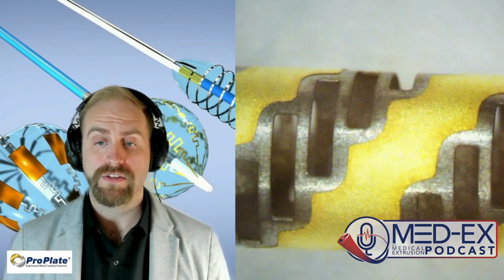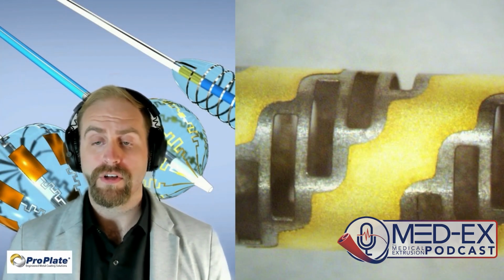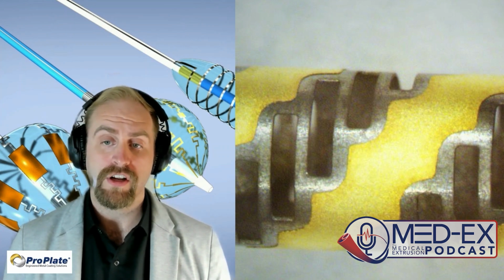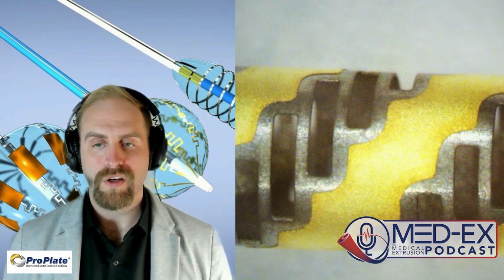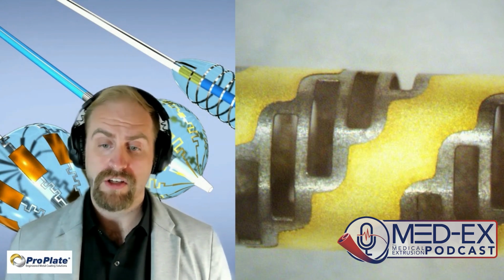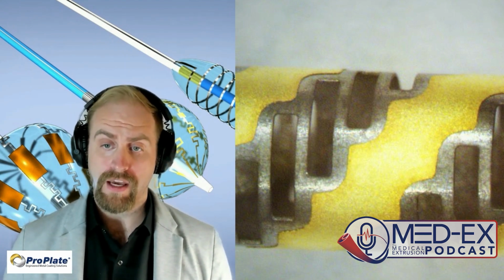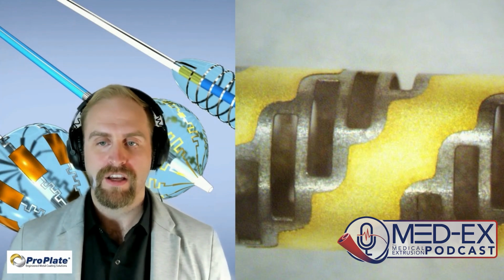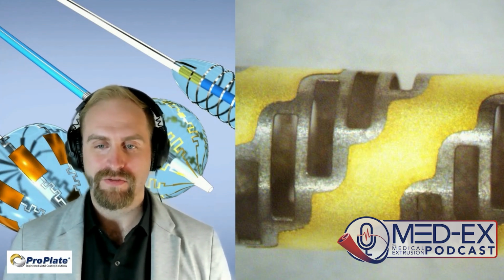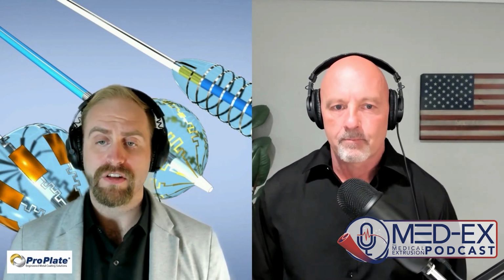And then there's some other advantages too in terms of shape. So with the coating process, we're not limited to band shapes. We can make helical patterns or spiral patterns, which then offer the ability to see device orientation as well as location. So what you normally have to do is take semi-circumferential bands, cut them up, and glue them on or weld them on. And it's a really tedious process that isn't very scalable, which kind of leads me to one of the other major advantages of this process: it's a highly scalable process.